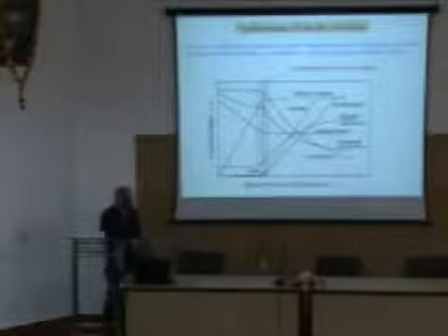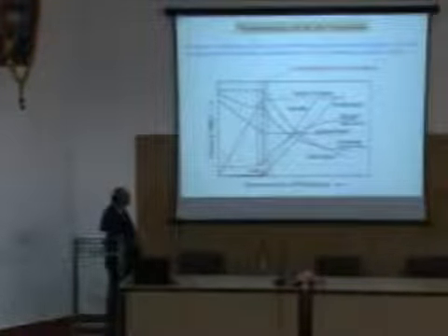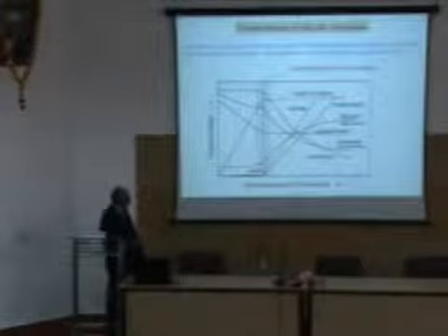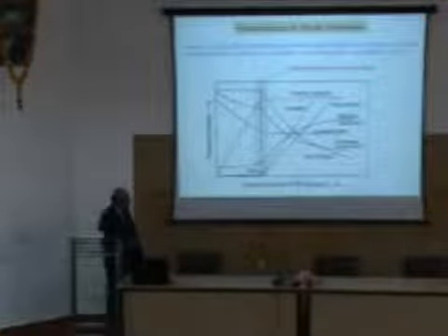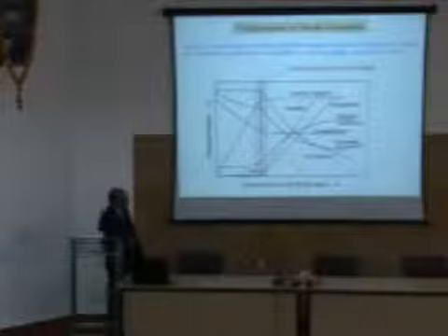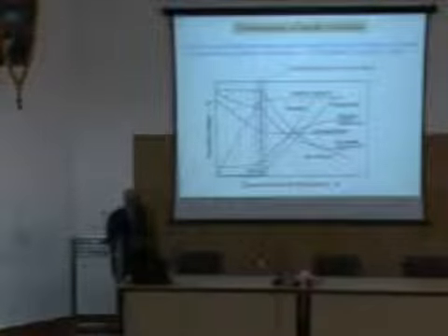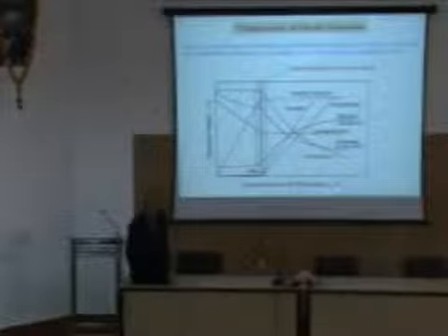So once you have an aggregate, how do you know that you have an aggregate? When you have an aggregate, you reach what is called a critical micellar concentration. At that point, the properties of the solution change drastically, and you can follow that change using many different physical methods. You can study the osmotic pressure, you can study the turbidity or surface tension, viscosity or self-diffusion coefficients, which will tell you that micelle has formed.